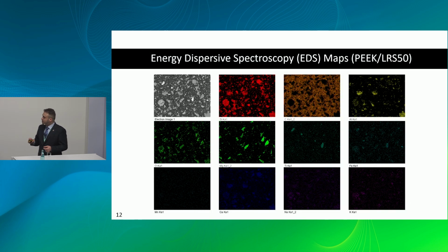Energy dispersive spectroscopy, EDS, maps of the composite. These are the areas where we have carbon, which shows the presence of the matrix. And for the particles, as expected, there is a non-homogeneous combination of various silicon and metallic oxides. We have silicon, aluminum, titanium, magnesium, iron, and other metals in the structure.